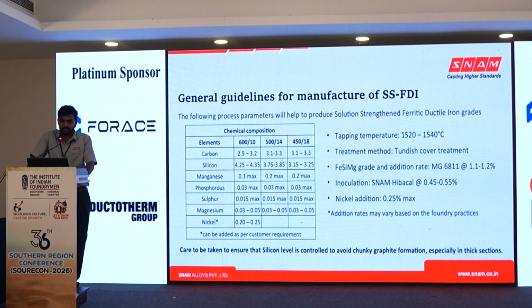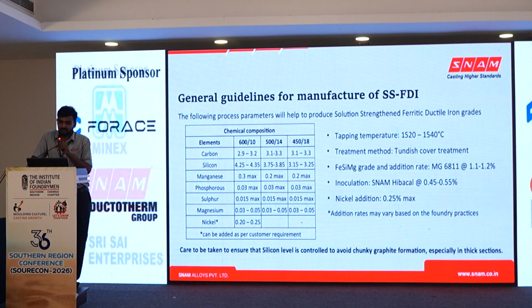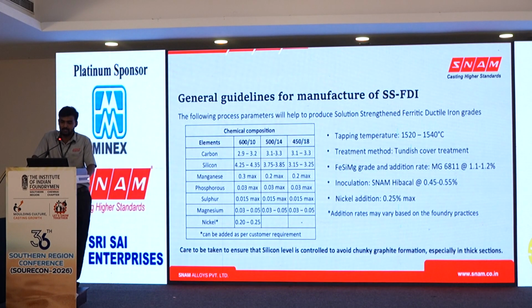Based on the experiments conducted, we tried to form general guidelines to produce SSFDI. The chemical composition is as mentioned in the table, and addition rates and process parameters will vary according to foundry practices. In our case we have maintained a tapping temperature of 1520, the treatment method is the tundish treatment method, and for FeSiMg we have used MG6811 and a barium-based Hibacal inoculant. For nickel, based on the grade requirement, we should add nickel.